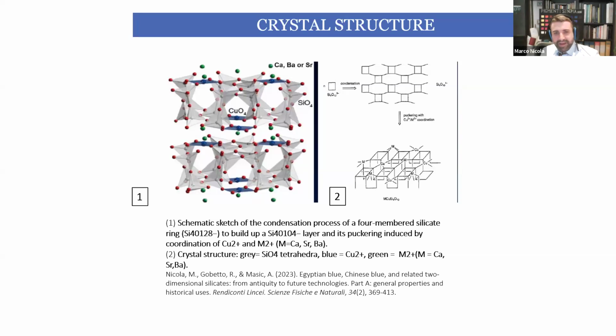And so we have a layered material that you can exfoliate in nanosheets and obtain quasi two-dimensional particles. The corrugation is depicted in this picture. So the layer is not hexagonal like the one in graphene, but is octagonal and square. That then corrugated gives the specific structure of the single layer of cuprorivaite.